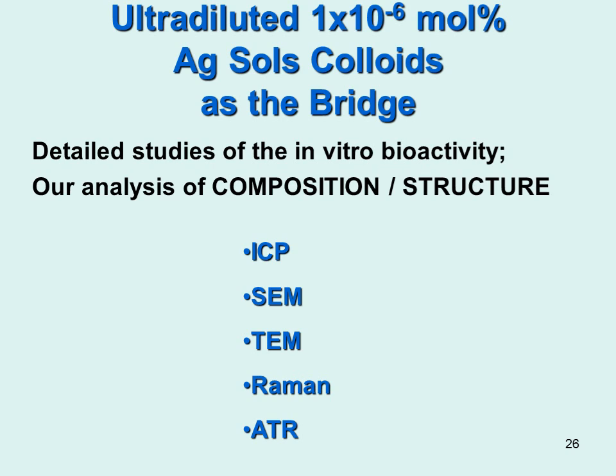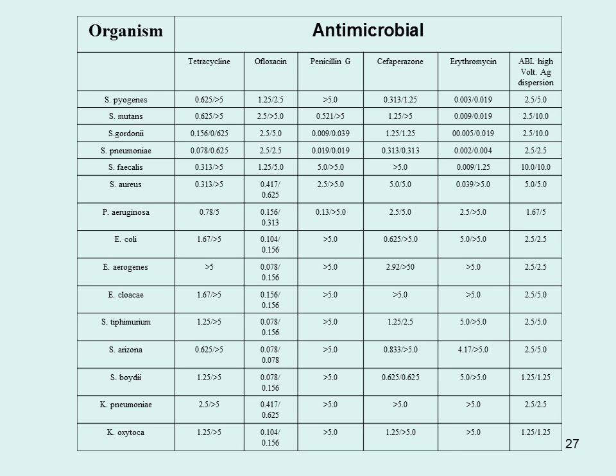We had found that a whole range of silver aquasols, I'm using the terms precisely, metallic silver aquasols, actually had very important biological properties. So we did a thorough characterization as material scientists would do, with tools. And this is just to start you off: an extraordinary biological activity of these ultra dilute sols. 1 ppm of metallic silver sols in ultra pure water is as good an antibiotic or antibacterial as there is. It kills most of the bacteria and a few viruses, and in fact it does very well on malaria now and even on MRSA. So that was impressive enough for us.